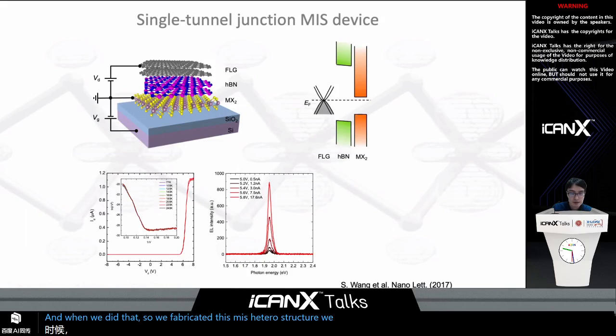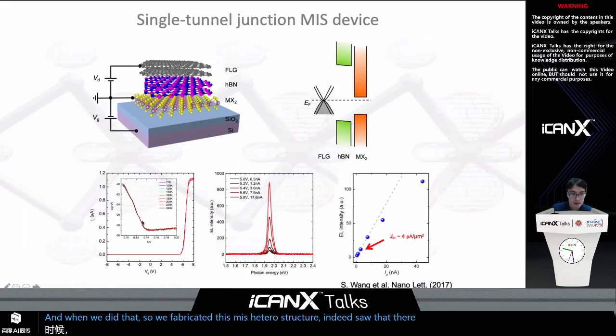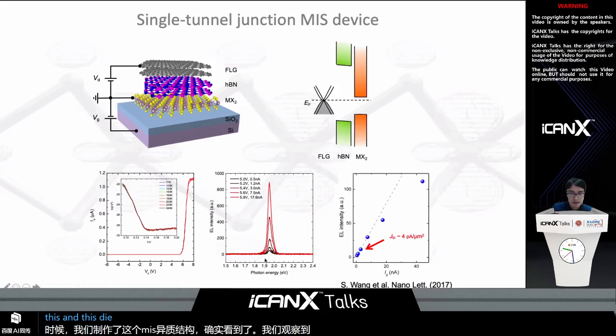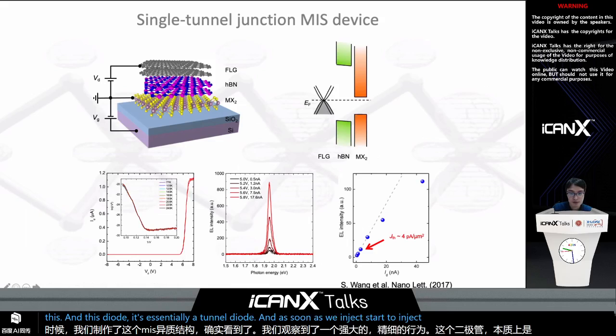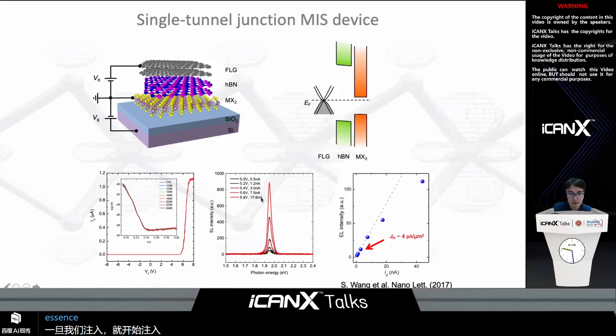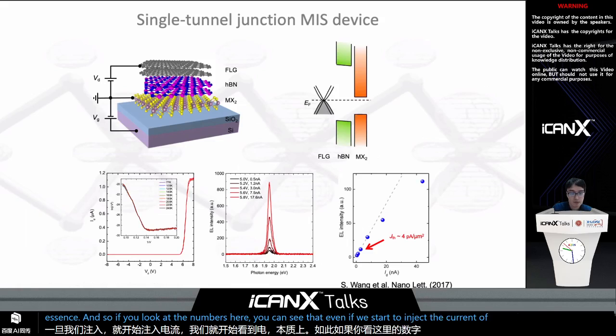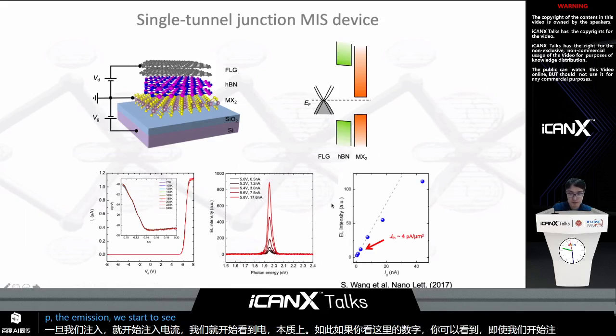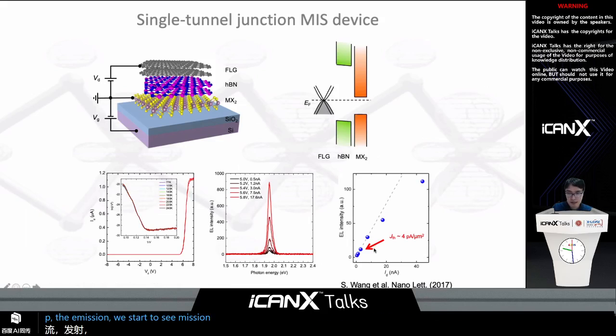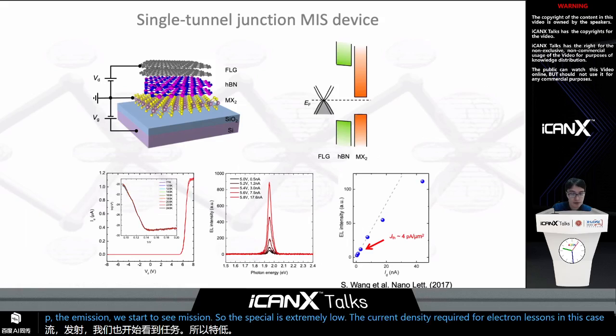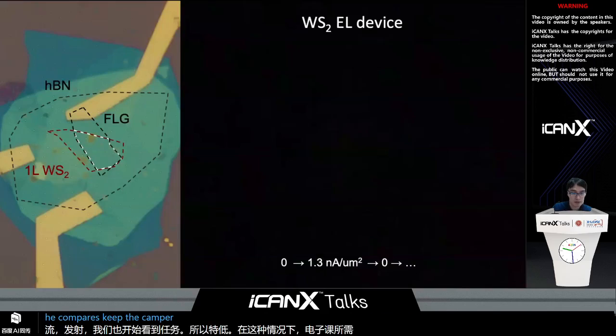We indeed observe a strong rectifying behavior in this diode. It's essentially a tunnel diode, and as soon as we start to inject some current, we start to see electroluminescence. If you look at the numbers here, even if we inject a current of the order of 0.5 nanoampere, we start to see emission. So the threshold is extremely low. The current density required for electroluminescence in this case is a few picoamperes per square micrometer.